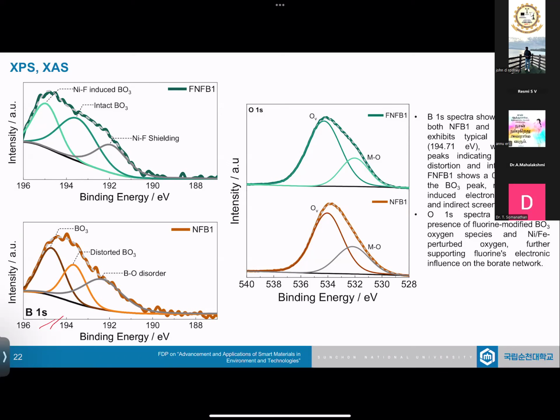And the oxygen states also can be seen over here, that you still have the metal oxygen bond and the boron oxygen bond, which are still present in a similar fashion, whereas the vacancy is being slightly altered. This states that at some particular points where there is BO3, that is, you have boron and three oxygens, there is a possibility that you can have a singular vacancy that might be induced by the inclusion of fluorine. Because we brought in iron, there is still some vacancy in the system, but because we brought in fluorine, there is also an increase in the vacancy. This is a small understanding that can be extensively discussed in our works. So these things we understand from the spectroscopy studies.